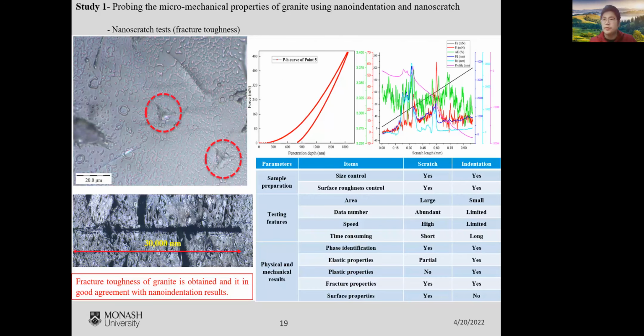Although nano-indentation is a powerful technique, it still has disadvantages. That is, it can only obtain the mechanical parameters of each single point. It cannot detect the mechanical parameters continuously. Therefore, nano-scratch tests have been carried out. We use the nano-scratch test to obtain the fracture toughness of our granite sample, and it is found that the two results agree well with each other.